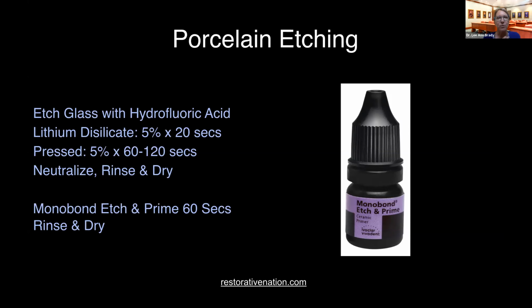So I will tell you today in my practice, one of the things I've asked my laboratory is to stop etching my e.max. Do not etch my e.max, because it's super difficult for the lab not to over-etch. They typically use hydrofluoric acid. They do 40 restorations simultaneously when they're etching. 20 seconds goes by super quickly.